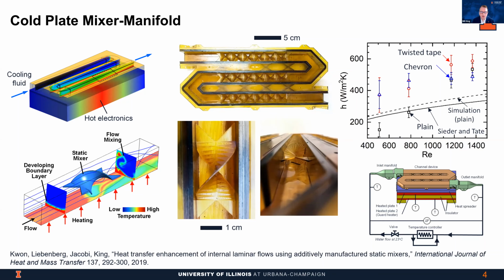The way these mixing structures work, you can see in the lower left part of the screen, we have a developing thermal boundary layer. There is this twisted tape mixing structure that interrupts the flow. It sweeps the hot fluid away from the hot wall and replenishes it with cool fluid, enhancing the overall heat transfer. So we built and tested a bunch of these devices. The paper here reports many details of simulations and design and testing, but just to give you the highlights, for this particular flow and architecture, we're able to improve the heat transfer within the device by about 2 or 3 times because of the presence of the mixing structures.